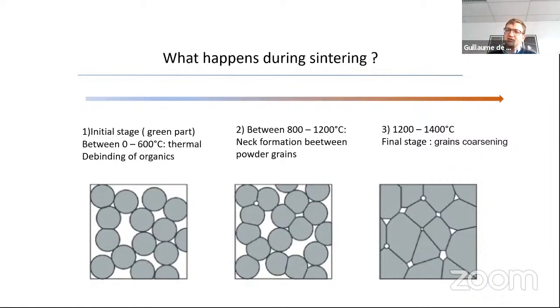And if you heat up more, you're going to get to a temperature where you are not melting the metal, but still the metal is at a temperature where it will start to move in a solid phase. What we call solid diffusion will happen. The grains are going to get bigger by, let's say, condensing together, agglomerating together, and there you will get a dense material. It's quite important to see that these stages are present because in some cases, a few offerings on the market will actually stop at the neck formation. So they will make very porous metal. It is always an option, and it may work for some application, but of course, the mechanical strength is going to be much lower than if you actually get to the dense solidification of the part, which usually happens in the range of 1200 to 1400.